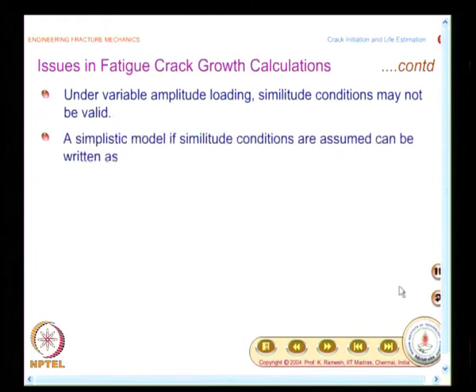As I mentioned, variable amplitude loading is going to be very, very challenging, and what you see here is under variable amplitude loading, similitude conditions may not be valid. And you know, whenever we face difficulty, we will first come out with a simplistic model. A simplistic model, if similitude conditions are assumed, can be written as in this form. Instead of writing da by dN, we write d a bar divided by dN, where a bar is the average crack growth rate.